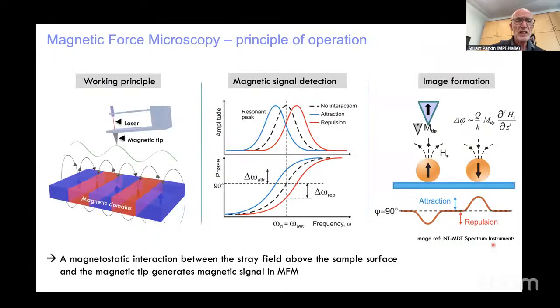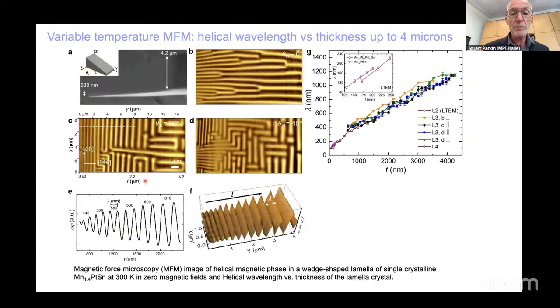So in the intervening time, we've used different techniques to explore these objects. We can use magnetic force microscopy, in which we detect the out-of-plane component of the stray field above the surface. We could use this to detect the skyrmions and antiskyrmions. And it turns out these antiskyrmions, before they're formed, the magnetic spin texture is actually a helical texture where the magnetization rotates from up to down in this one-dimensional fashion. And in the magnetic force microscope, if you look in E, this is the component of magnetization. It rotates from up to down as you move along this